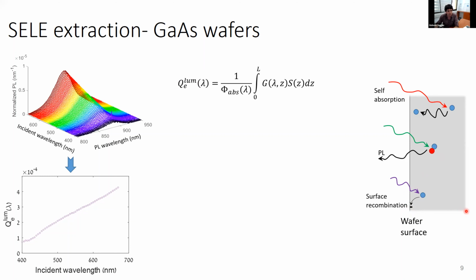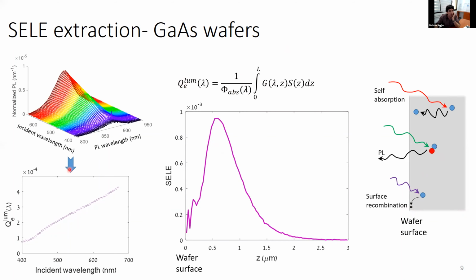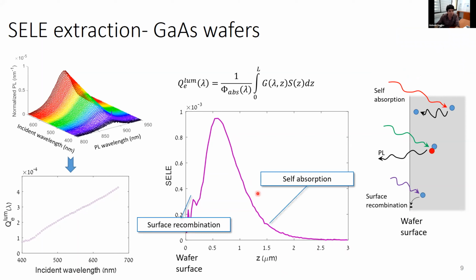So we extracted the SELE out of the spectrum here, and as you can see, with the surface being at Z equals 0, we can see a very strong indication of surface recombination losses, the decay due to self-absorption, and actually the height of the peak can be attributed also to optical coupling, how easy it is for photons to be emitted from the device, which might also be relevant for people working on LEDs and stuff like that, and also very important for solar cells as well.